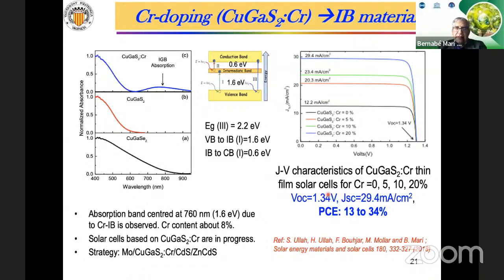Which means that the photoconversion efficiency can change from 13% for this material without chromium to 34% with chromium. This is from the theoretical point of view, because in practice this material is too resistive to be able to produce good solar cells.